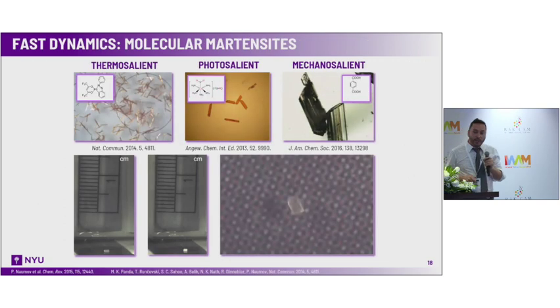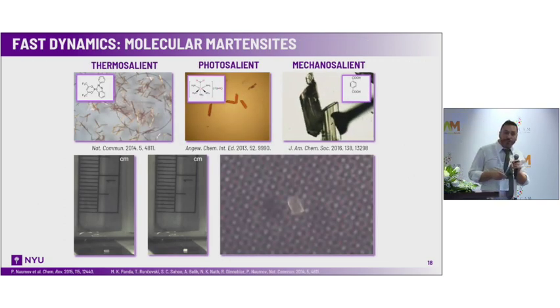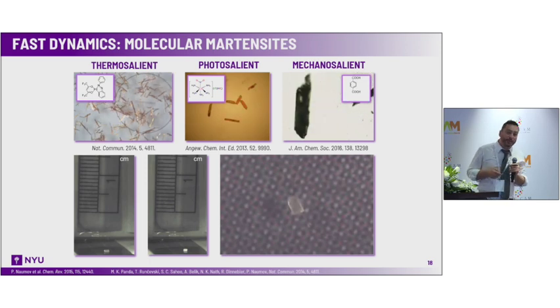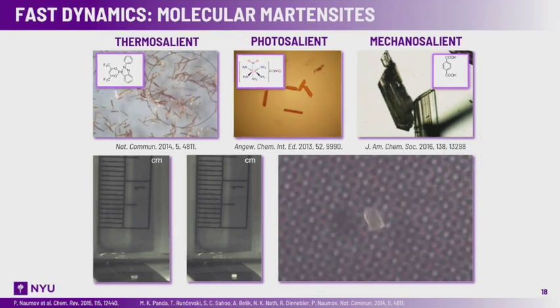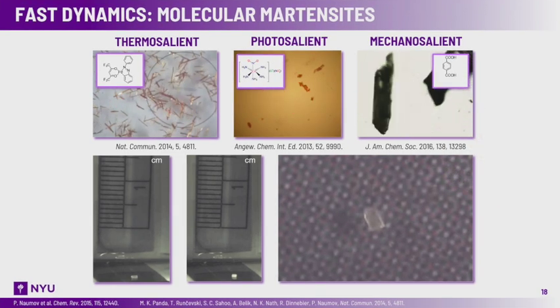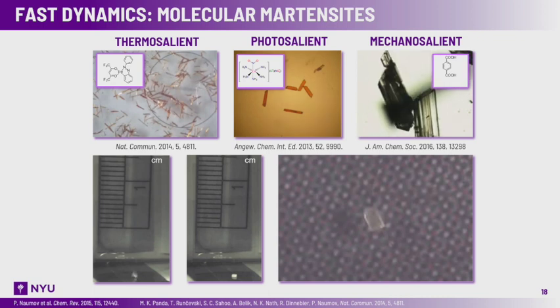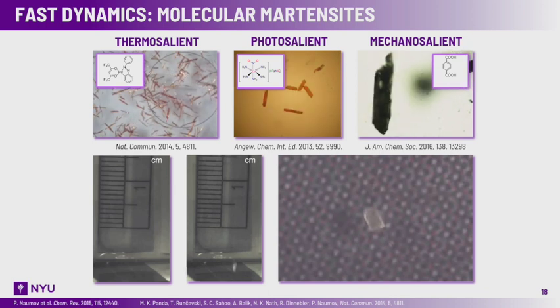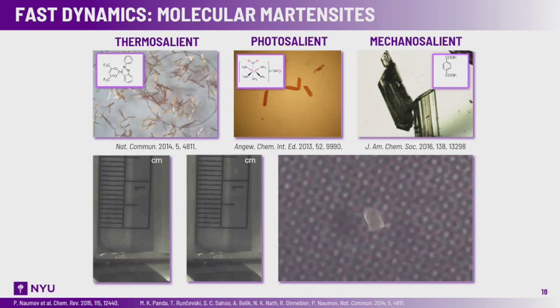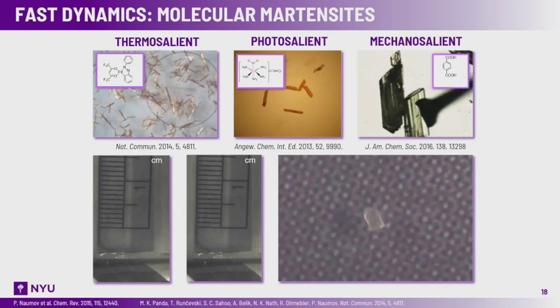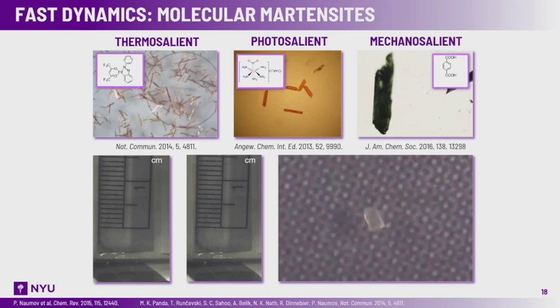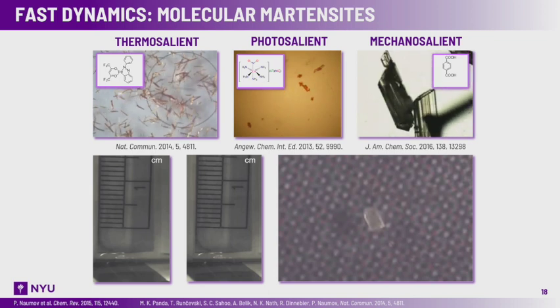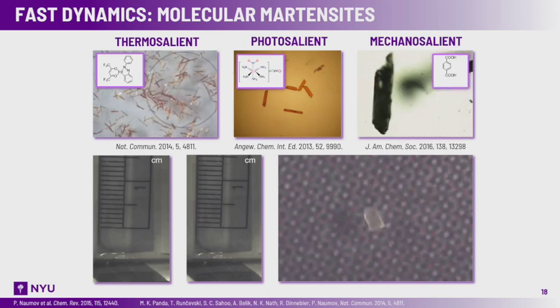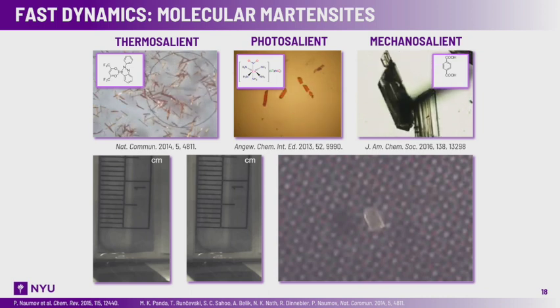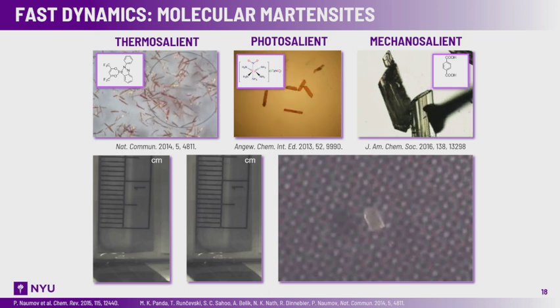research. Our particular interest in materials, especially crystals, is very fast phenomena. About 10 years ago, we discovered that if you subject some crystals to heat, light, or even mechanical pressure, they can move, and they do so from several millimeters up to several meters. It's very important to understand not only why this happens, aside from the visual appeal, but also the amount of elastic energy that is accumulated within the material and released in the form of kinetic energy, which makes these things move.